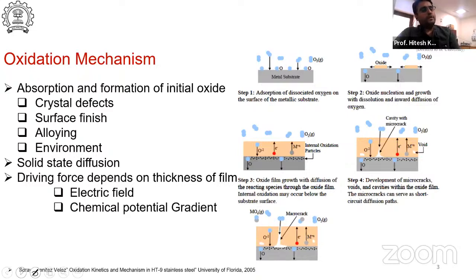It is basically affected by the crystal orientation or crystal defects. If there is some misorientation in your material, then it provides space for the oxygen to interact with, because it is a high energy site in the material. The surface finish, alloying elements and environment also affect the oxidation and corrosion behavior of the material. Earlier literature mostly talks about surface finish, alloying and environment, but the crystallographic texture part is still not identified. Other than that, it is a solid state transformation where the driving force during oxidation is either the electric field between anions and cations, or the chemical potential difference between the layers. That affects the oxidation mechanism.